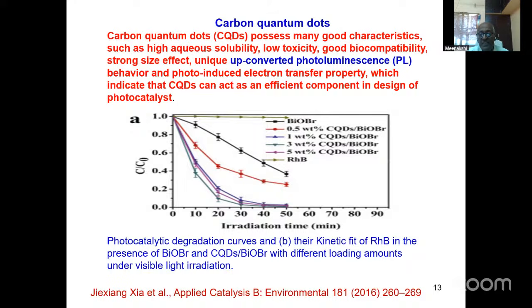When you excite at 300 nanometers, you may get 400 or 500 nanometer emission for carbon quantum dots. At the same time, when you excite at 600 nanometers, you get an emission at 300 or 350 nanometers. That is at the lower wavelength, higher energy radiation. The fluorescence, the photoluminescence, is upconverted to the higher energy radiation. So this is possible with carbon quantum dots.